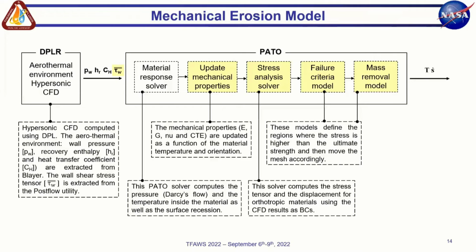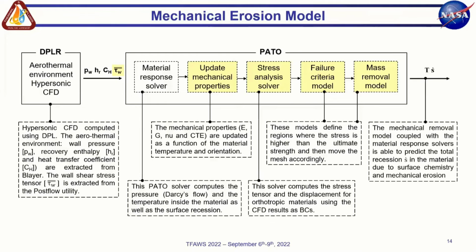The failure criteria and the mass removal models define the regions on the surface where the stress is higher than a threshold, and then move the mesh accordingly to remove this material. And the outcome of this is the total recession of the material, which also accounts for the mass loss due to the mechanical erosion.